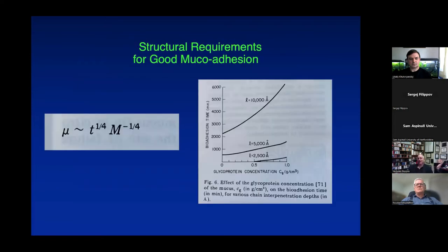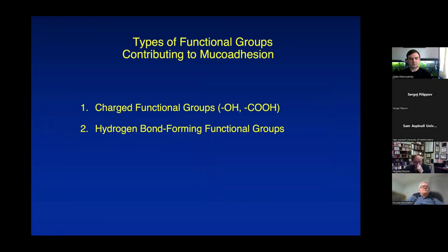One of the things, for example, that came out of this analysis is the strength of the adhesion bond. And we found that it's proportional to the time of contact to the 1/4 power and proportional to the molecular weight to the minus 1/4 power. These are called scaling laws, and they are similar to the laws that somebody like de Gennes would have made. Coming back now in the next 20, 25 minutes to the final comments about the application of this.